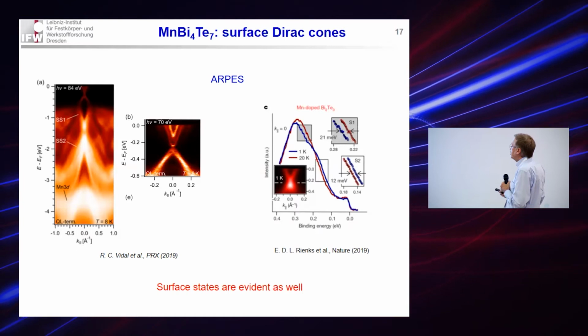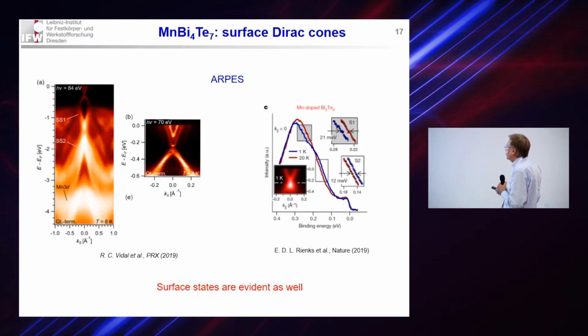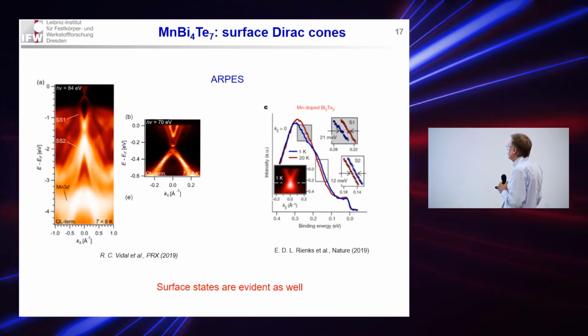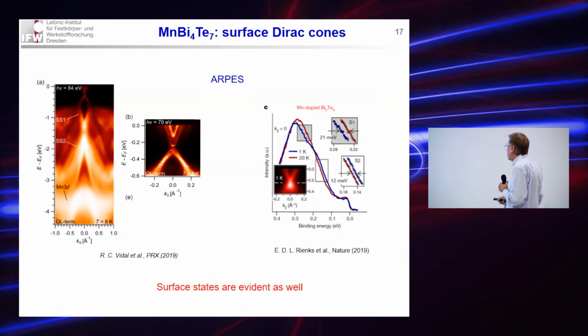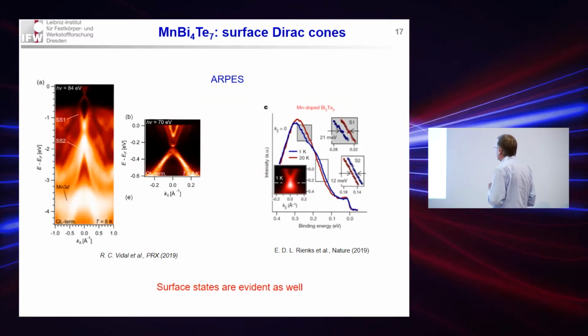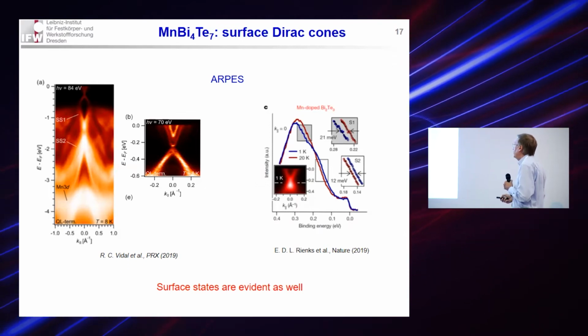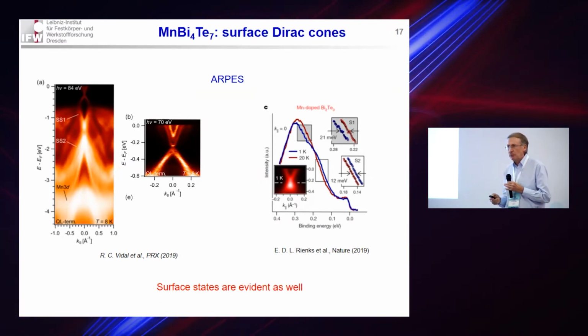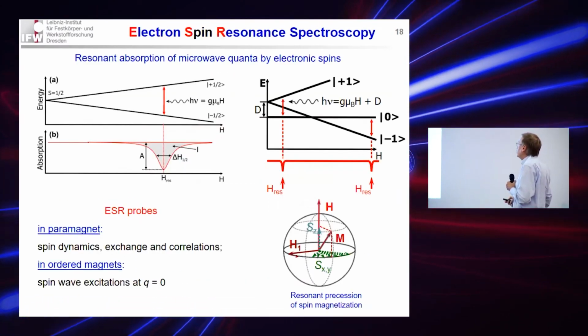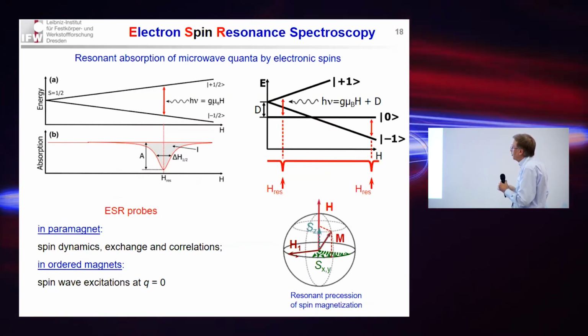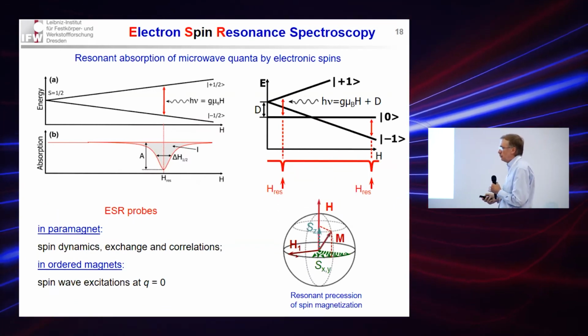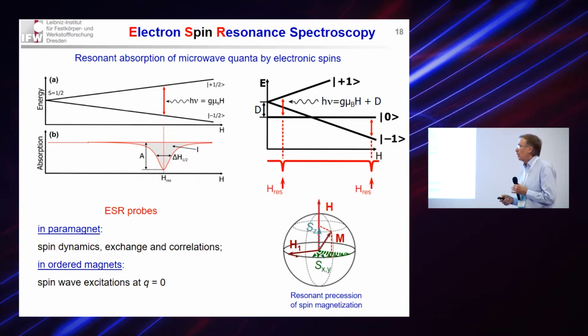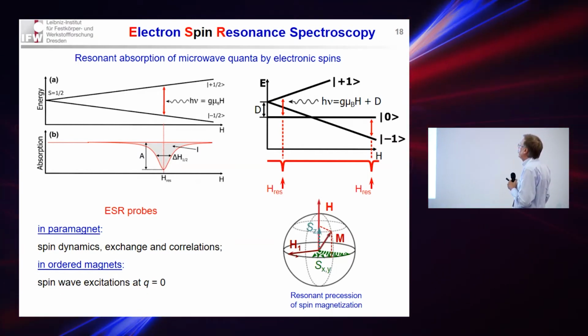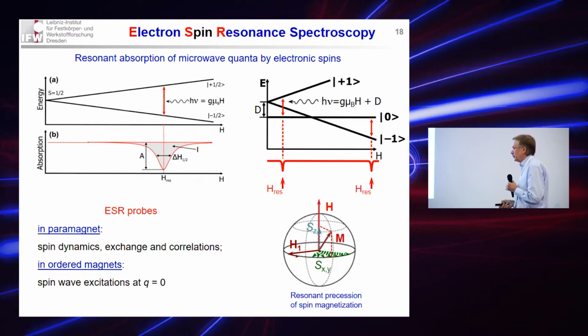Now similar results were obtained on 147, which contains in addition one non-magnetic interlayer. In the ARPES experiment, again, indications of the surface Dirac cones were found by our group, but also by other groups. So the surface states are evident as well in this material. And then we wanted to have a bit more insight into the magnetism of this material by measuring electron spin resonance spectroscopy on these systems.